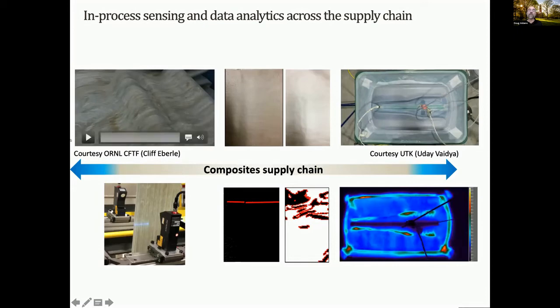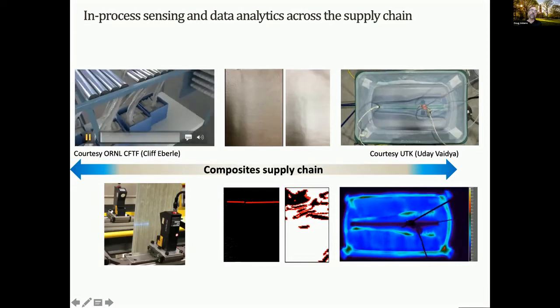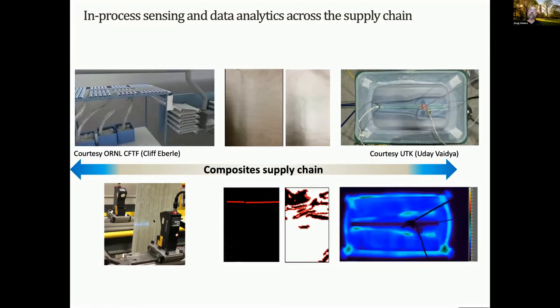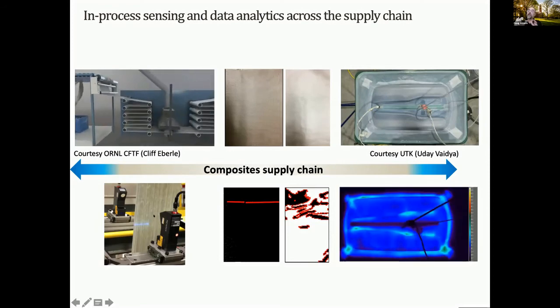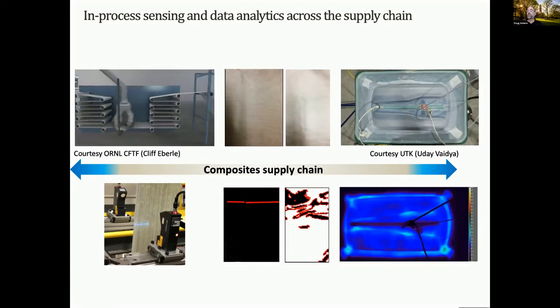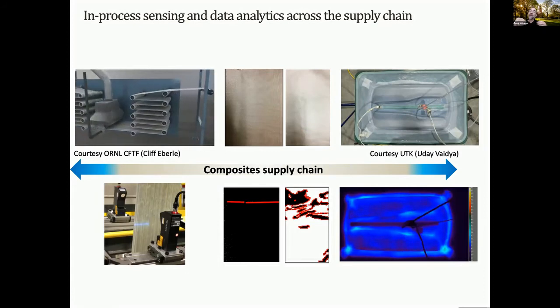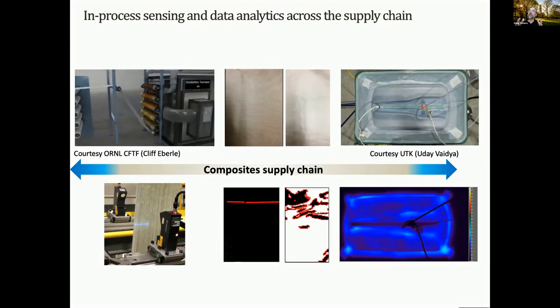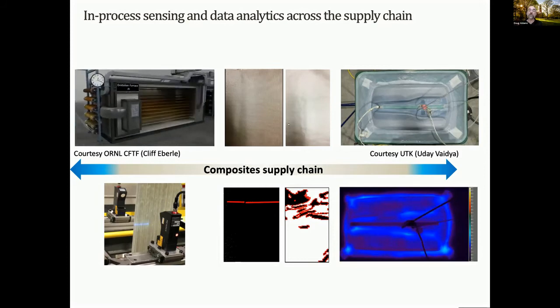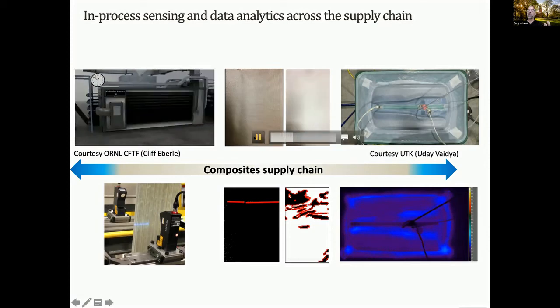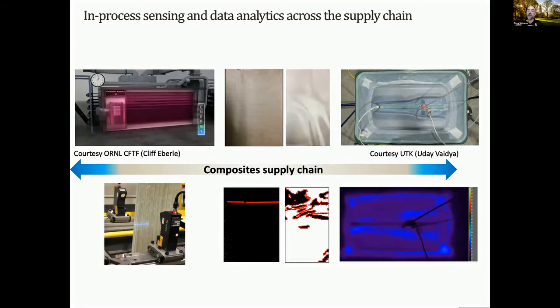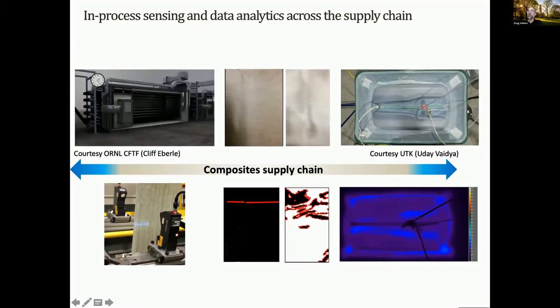You can also apply this idea to, as we heard the earlier speaker, the manufacturing of carbon fiber using a different type of measurement, not maybe a thermal measurement, but in this case, a profilometry measurement, looking for imperfections in the geometry, in the form, for instance, of the precursor material here in carbon fiber. Or you might be able to use machine vision to actually look for changes in fabric that might suggest there's wrinkling or there's fiber pullout in those fabrics. And you can use machine vision in order to identify those in process.